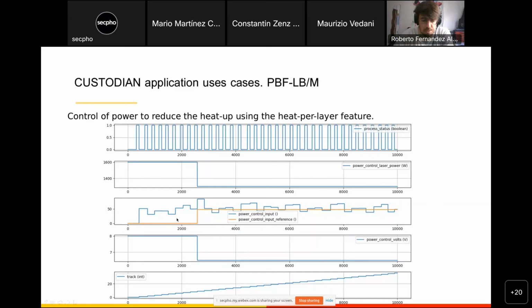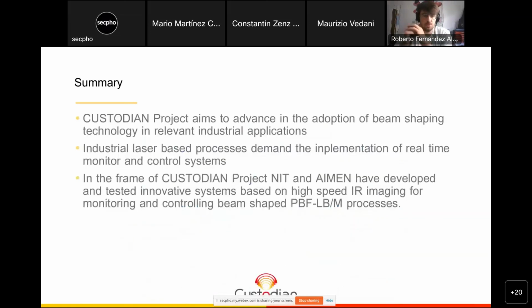It's not finished yet. In this test that we did here, after the 8th track, the control enters, and in this case there is a big difference between the reference and the next layer value, so it goes totally down. But in fact, it works because it stops the feature from going up like in the other tests. So nowadays we are working on tuning the controller constants to have a more continuous control. So this is all from me.